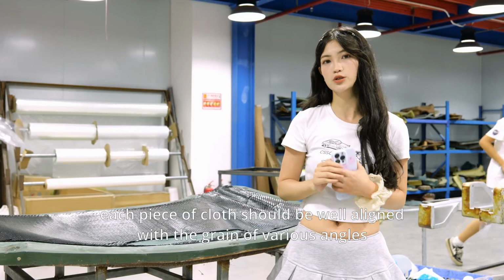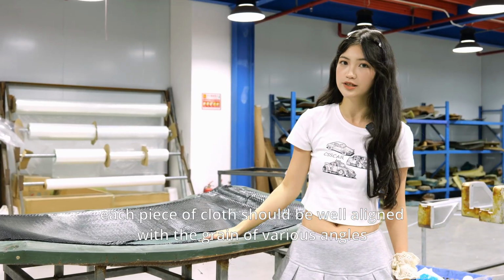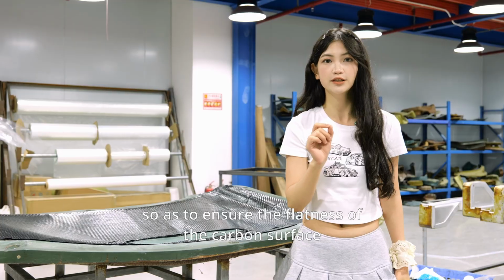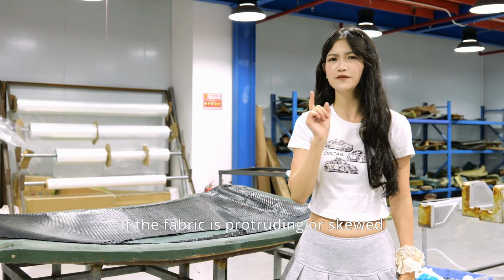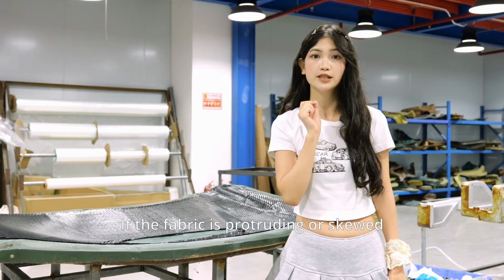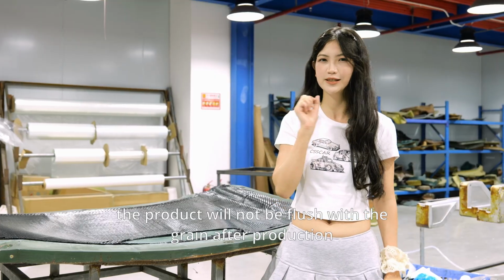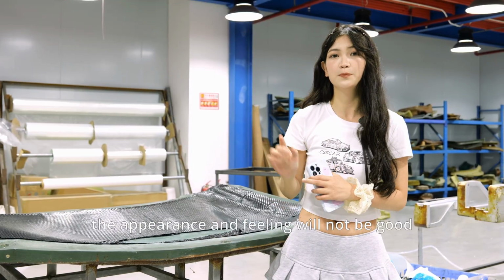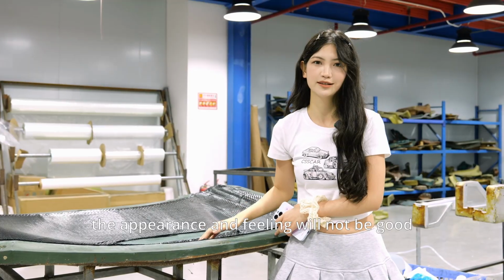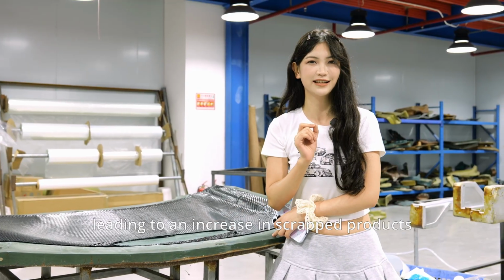Each piece of cloth should be well aligned with the grain at various angles, so as to ensure the flatness of the carbon surface. If the fabric is protruding or skewed, the product will not be flush with the grain after production. The appearance and feel will not be good, leading to increased scrap of the product.